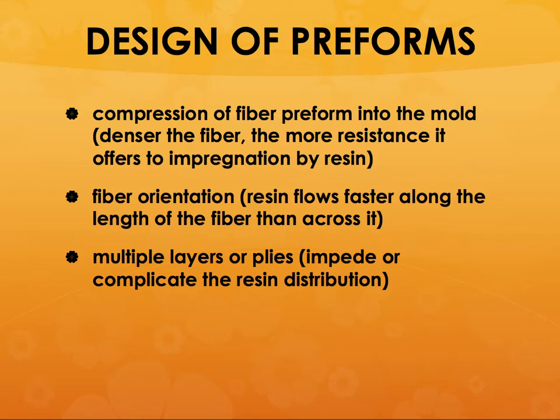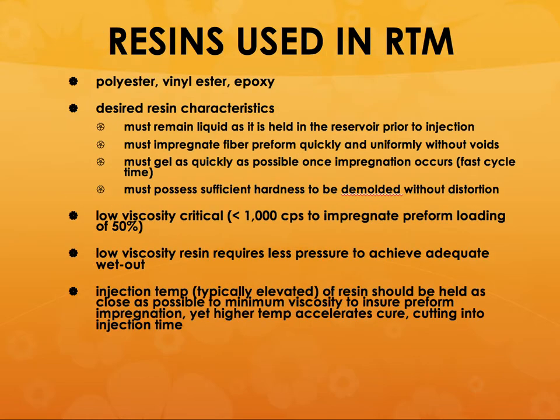And then you have to compress the fiber preform so that the fiber is denser. But the problem is that if you have a very dense fiber preform, it will not allow the resin to be infiltrated or impregnated that easily, which means you will have to have a very low viscosity resin system. The fiber orientation also is important here, because the resin will flow faster along the length of the fiber rather than across it. And if you have multiple layers or plies, it will impede or complicate the resin distribution. If it is very closely packed together, it won't wet all the fibers. So there are a few issues, and you have to make sure those issues are taken care of.